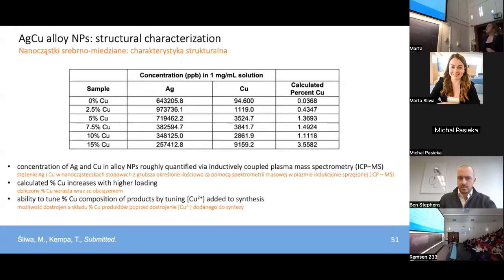So it's important to note here that the calculated percent is actually a lot lower than what we nominally load. Again, that word comes up. For example, for the 5% copper that we introduce, we only get roughly 1.4% in the actual products that we yield. This is most likely due to loss of copper during the synthetic process. Copper is known to form complexes with oleate, which is, again, in excess in the solution. There's also probably loss of copper during the purification steps, as well as some copper being retained in that silver bromide host. It doesn't make its way to that silver copper alloy and therefore lowers the amount that we actually incorporate.